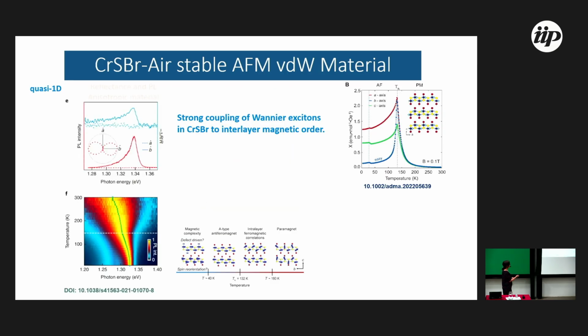So, for example, just to show, this is the magnetic response. If you look along the A axis, B axis, or C axis, the phase transition occurs at the same temperature, the Néel temperature, but the magnetic properties are not equivalent in different directions. And for optics, you can measure reflectance or PL, as I showed you. You only observe PL when the linearly polarized light is along the B axis.